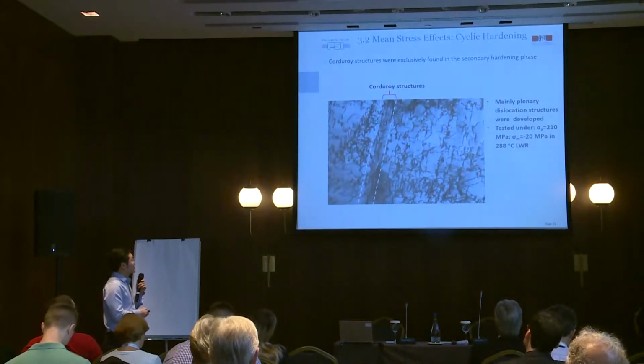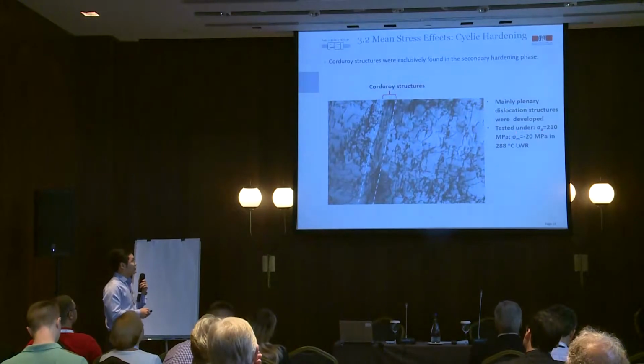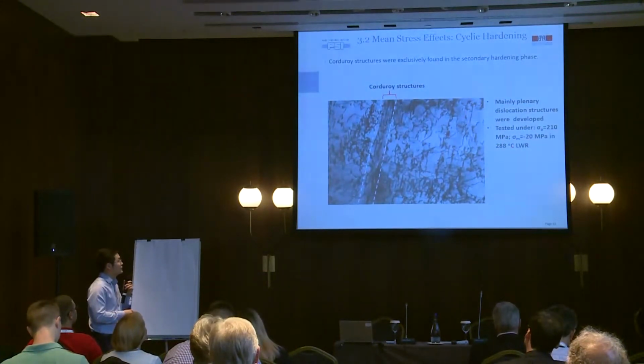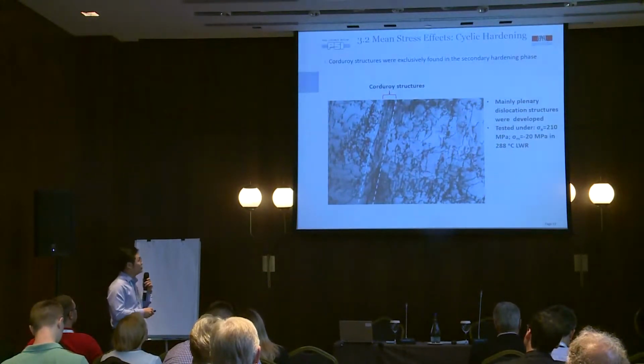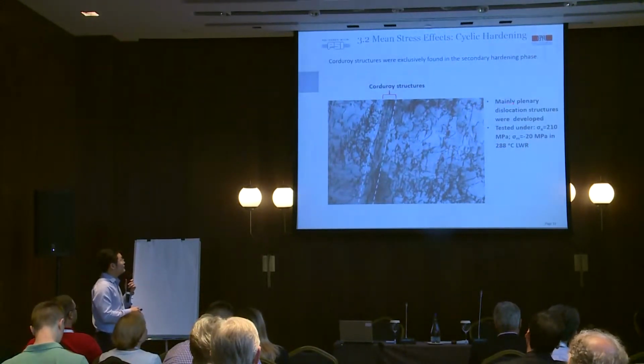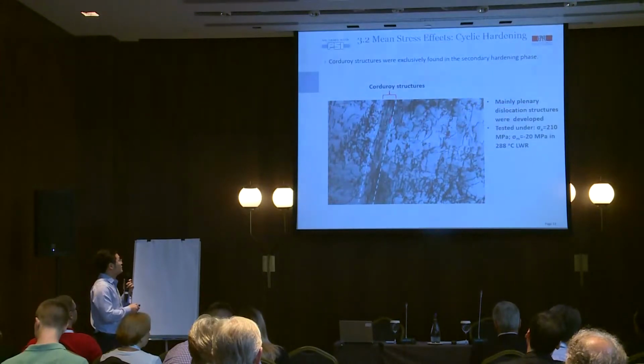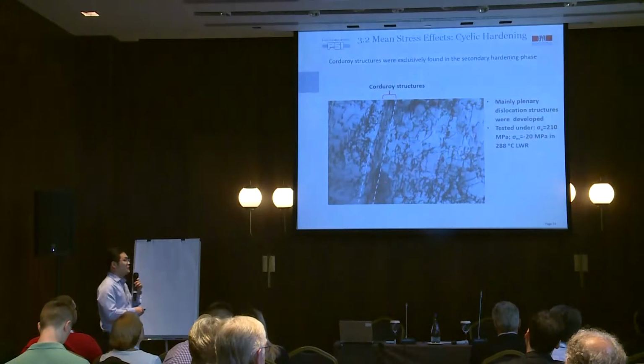And I take an example picture. This specimen was tested with a stress amplitude of 210 MPa and mean stress of minus 20 MPa in high temperature water. Many planar dislocation structures were developed, and the corduroy structures were exclusively found in the second hardening phase. This kind of structure may be responsible for the second hardening.